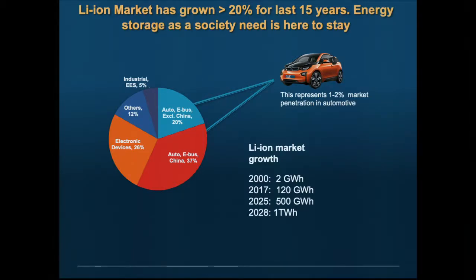And the growth numbers here, right, in 2000, we barely produced 2 gigawatt hour of lithium-ion, which is about 200 million smartphones, basically. In 2017, this number is probably a little underestimated. It's somewhere between 120 and 150 gigawatt hour. We made projections in a paper 2 years ago that by 2025, 500 gigawatt hour would come online. The reviewers of the paper said we were crazy. And now we're actually being criticized for that number being too low already. And people are projecting about 1 terawatt hour of production, right, by 2028.